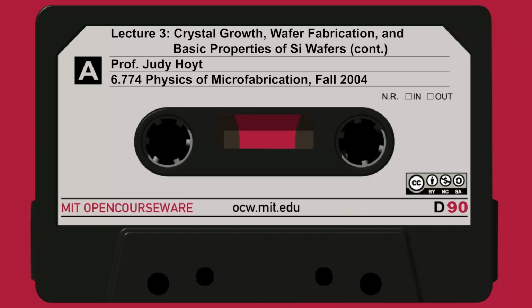In fact, we're going to reference them to the band edge. So as I increase the temperature, remember the band gap shrinks. I'm going to say that this distance between the band edge and the vacancy level maintains a constant, even though the band gap is shrinking. Again, that's an assumption, but we're going to assume the defect levels track their respective band edges.